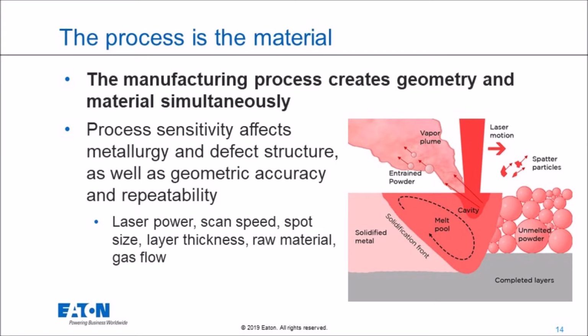Looking at the process itself, these are the details of the laser powder bed process. It's very dynamic, very chaotic, and very stochastic, which means that you get slightly different results every time, and you have to control this process very well in order to get the same part every time. You have slightly different distributions of particle sizes and gaps in the powder bed itself. When the laser comes down and hits and creates this melt pool, you have a cavity here, which is a depression in the melt pool. The liquid in the melt pool is recirculating due to Marangoni flow. You have a solidification front. You have a vapor plume coming off and throwing powder into the air. You have spatter particles, which are partially melted, flying out the other way.